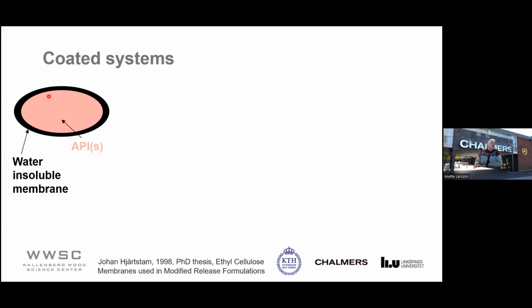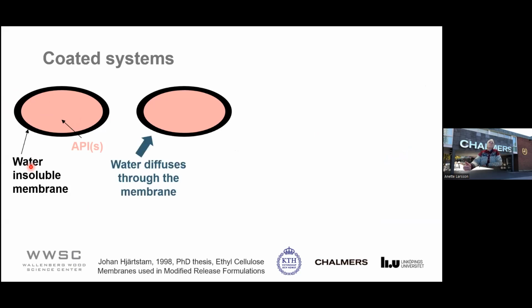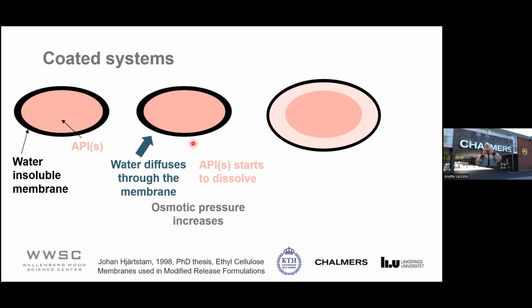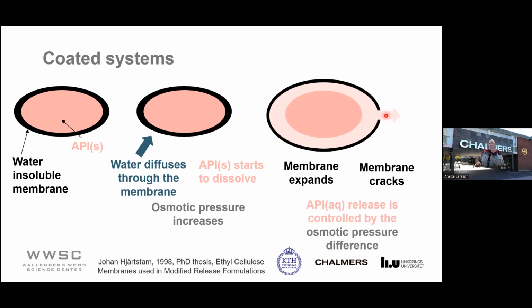So I start with this one, where you have the active substance here and the insoluble matrix, and you place it in water. And the first thing that happens then is that the water starts to diffuse through the membrane. And this then makes the APIs start to dissolve. And then you create an osmotic pressure inside here. This osmotic pressure will expand the unit, the membrane. And then it expands more and more, and then it snaps and cracks. And you get a crack here, and through this crack, you will get a drug release. So in this case, the release rate is controlled by the osmotic pressure difference inside and outside the formulation. So therefore, we call this an osmotic controlled release.